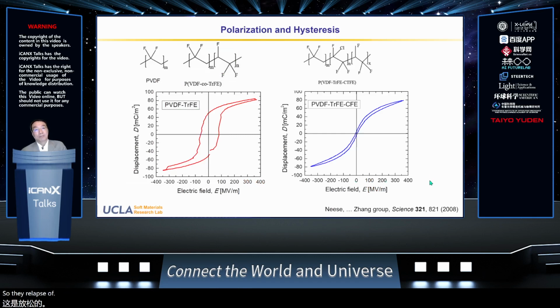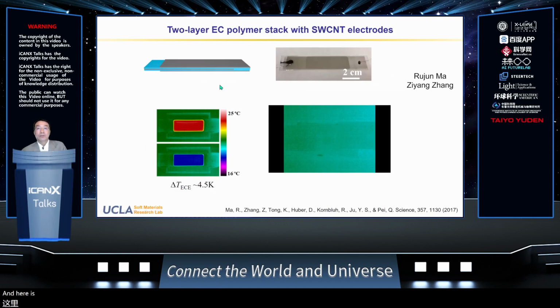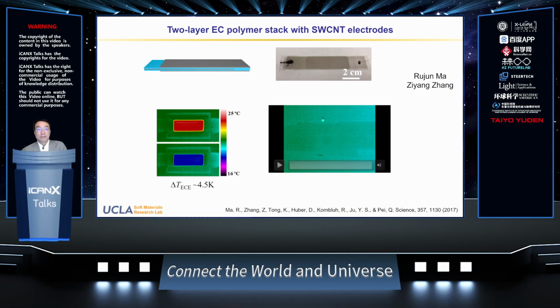The relaxor ferroelectric polymer, like this PVDF-TrFE-CFE terpolymer, has a very small hysteresis. So it's a relaxor ferroelectric. And here is a 2-layer stack of this terpolymer and 3 layers of carbon nanotube electrode. Let me play the video here. When you apply the voltage, the active area is heated because of the dipole orientation. When the voltage is removed, it cools down. So you can use the voltage to reversibly control the temperature up and down.